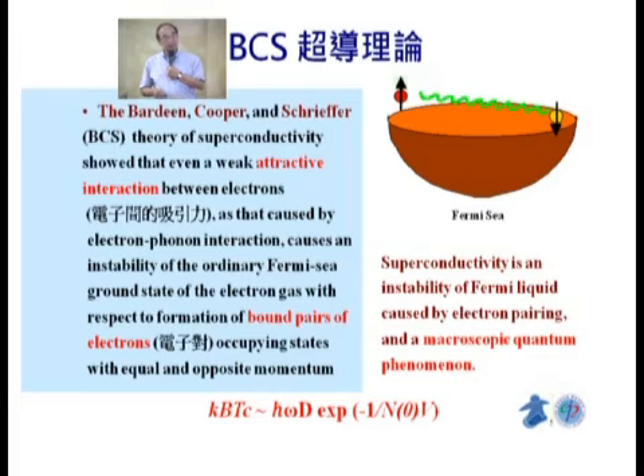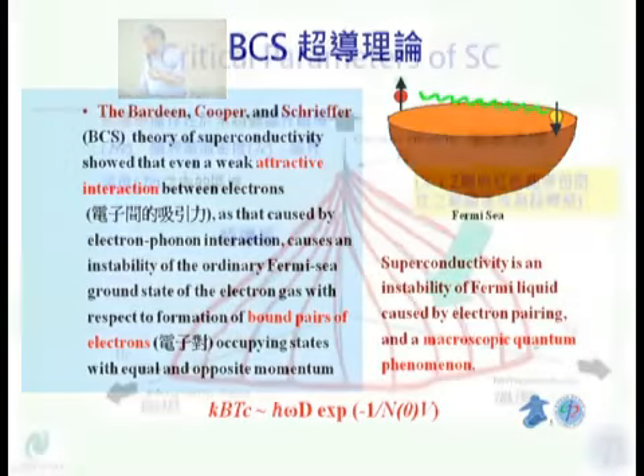There is a very simple linear relation here. And you also like to have this parameter larger, because this is exponential minus. So as it becomes larger, this factor becomes smaller, and that factor becomes smaller, so you have a larger Tc. That became a very important criterion in the late 50s and 60s when people tried to find new materials.